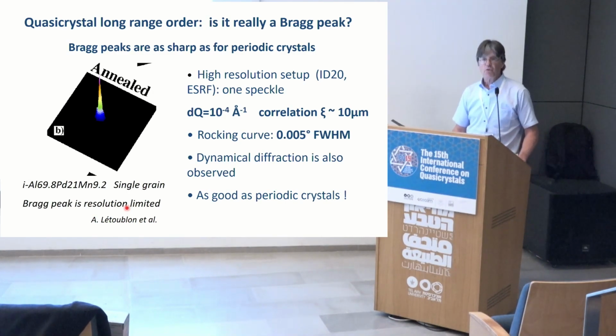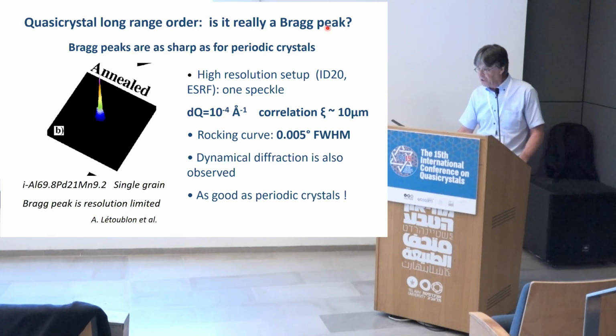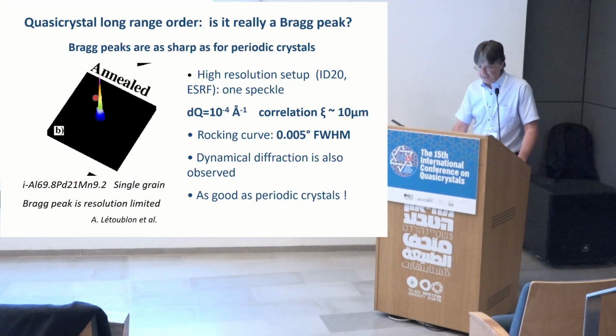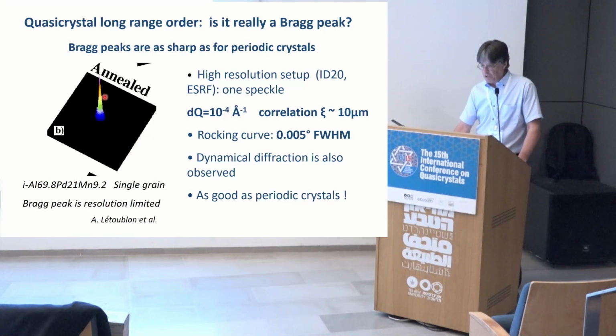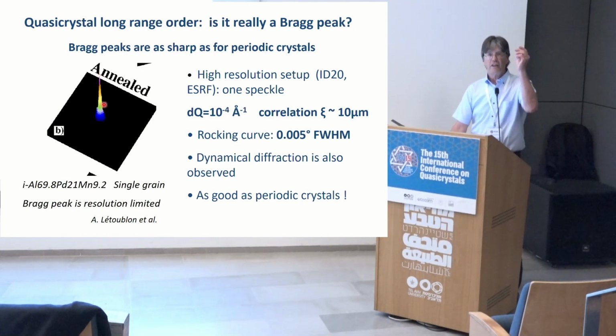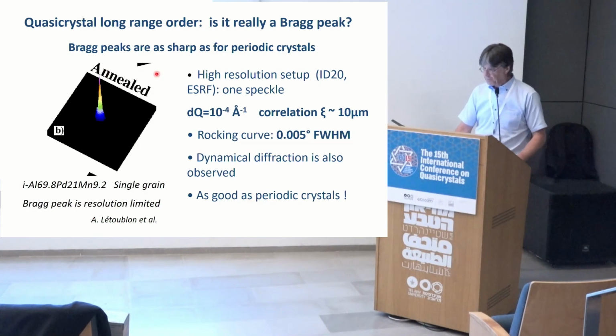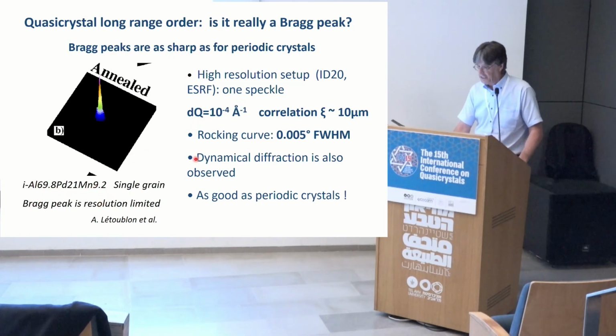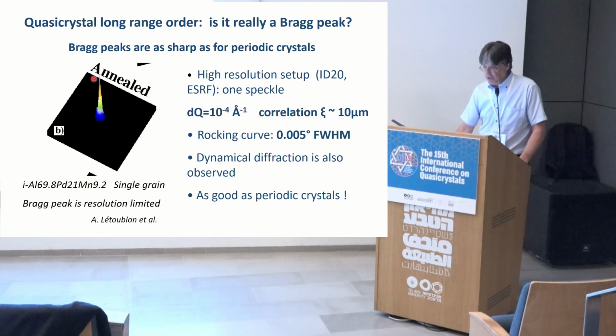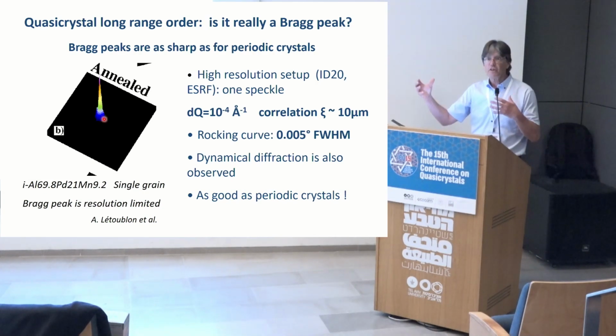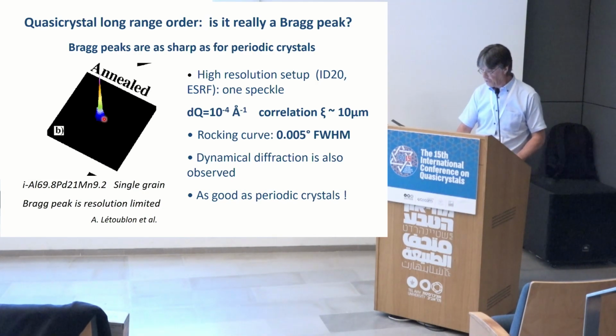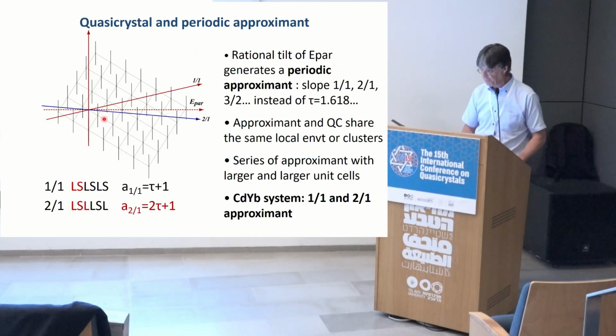there was a long-time question: is it really long range order? Is it really a Bragg peak? And that's quite a nice answer, I think, to this question. What you're seeing here is just a single pixel detector Bragg peak taken in an extremely high resolution setup of one of the aluminum palladium manganese once it has been annealed. From this, you can derive that the correlation length from the width of this Bragg peak is 10 microns. So it's really, really long range order, as good as for periodic crystals.